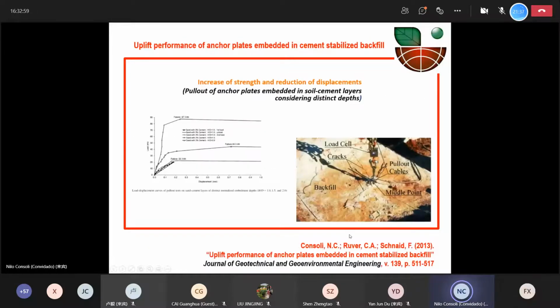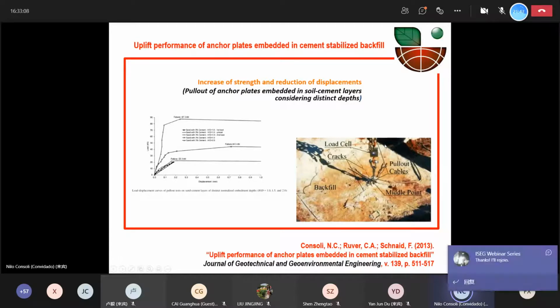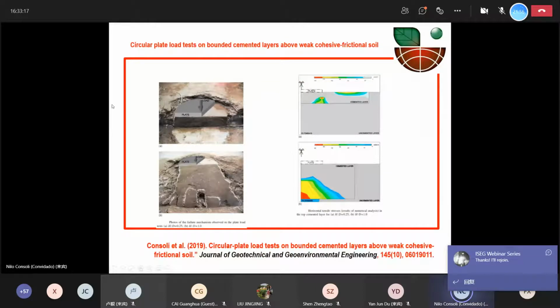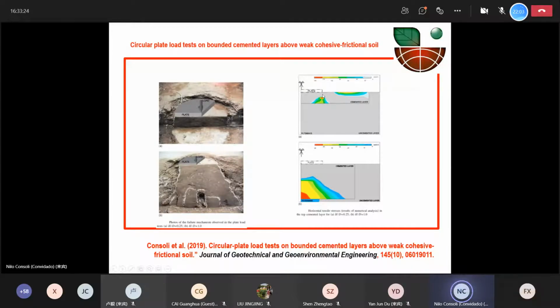After that, in 2013, we also published the journal. So we have done this in the field, and we have shown also that it's quite interesting, and we have a good solution. Here are other cases in which we improved layers, and then we put shallow footings on the top. We have some numerical analysis showing where the tensile strengths are, where it starts the failure mechanism. That was published in 2019 at the Journal of Geotechnical and Geoenvironmental Engineering.